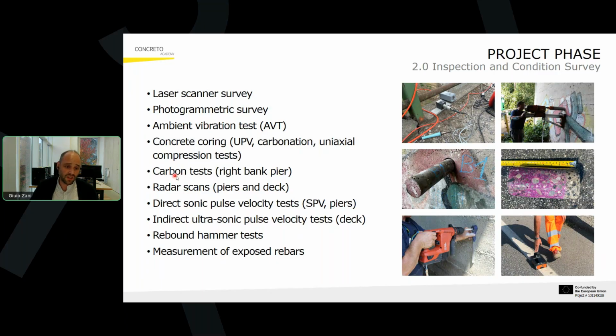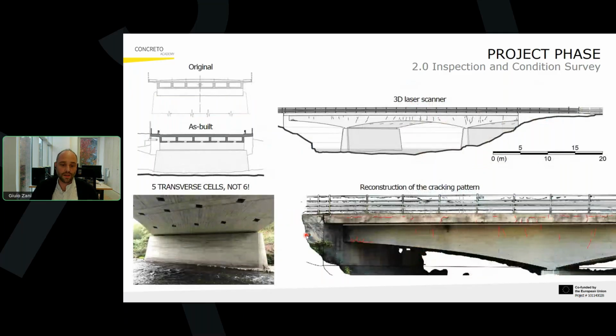Then we performed some carbonation tests on the piers, some radar scans. So this is again a GPR on both the piers and the deck, and then a series of sonic and ultrasonic pulse velocity tests on both, again, the deck and the piers. We also performed some rebound hammer tests at specific locations, in particular close to the concrete coring, and then distributed throughout the whole structure. And then where possible, we also measured the exposed rebars to understand the differences between the original design and the final constructed, as-built situation.